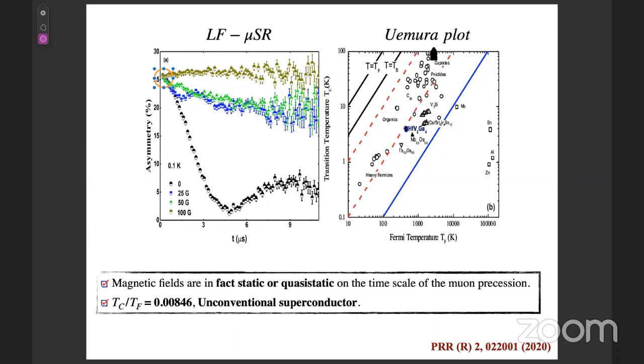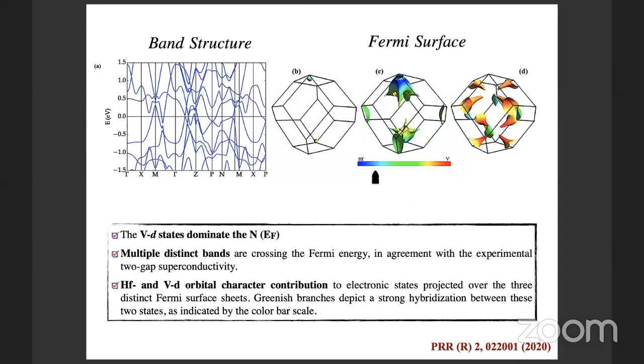Also, here we plotted the Uemura plot, and we find that our system, like hafnium vanadium two gallium four, is very close to the line where the cuprates, pnictide superconductors and heavy fermion superconductors lie. So all these experimental observations suggest unconventional superconductivity in this system. We also did band structure calculations and find multiple distinct bands crossing the Fermi level, which supports the two-gap behavior observed in the μSR experiment, with dominating states from vanadium near the Fermi level.